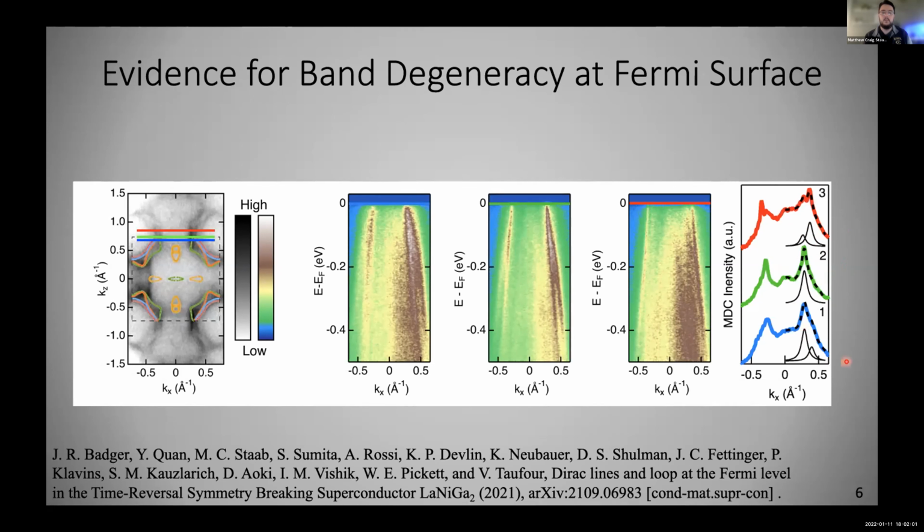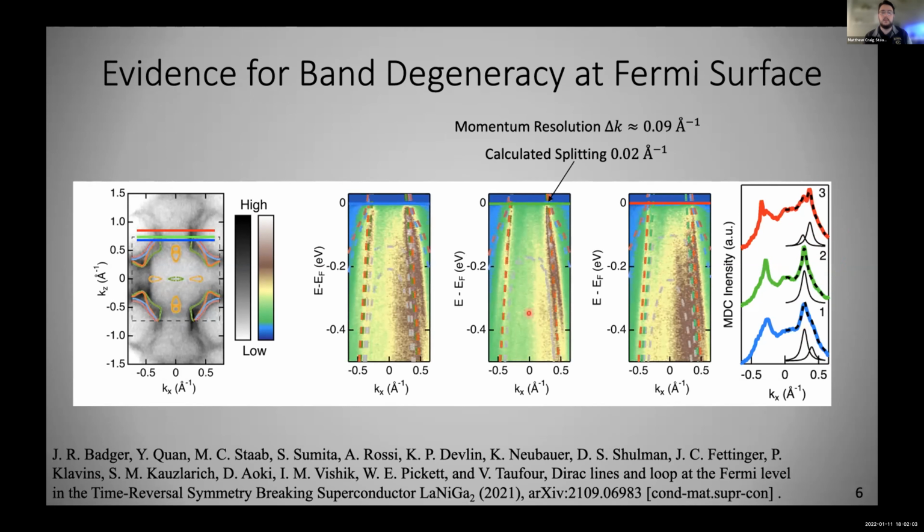One more quantitative agreement we can do is overlaying the DFT on the actual spectra. It's common in ARPES not to see every band expected in DFT, but it's not very common to see a band and it not be there. So the bands we do observe correspond to this green and red dashed line pair in all three cases.